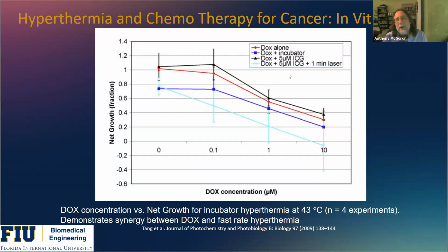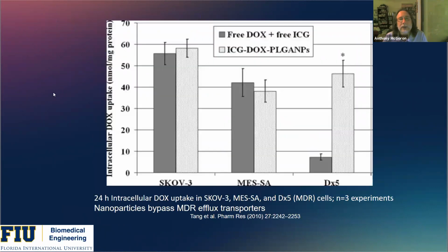But if we do the same experiment by exposing the cells to the doxorubicin, the indocyanine green, and 1 minute of the laser, which I showed before, increases the temperature quickly up to 43 degrees, we have a much greater response. So we see some synergy between the doxorubicin and the fast rate hyperthermia, but not a synergy between the doxorubicin and the slow rate hyperthermia. So I'm very interested in learning more about what's going on at the cellular biological level as a response to these different types of induced hyperthermia. Someone watching might have some ideas of how we could pursue this further.